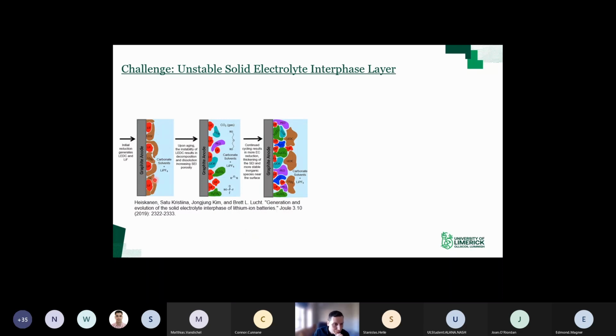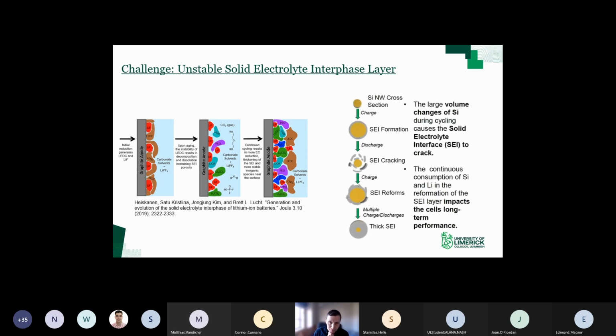Okay, so basically what happens is when you charge a lithium-ion battery at the anode, you'll get decomposition of the electrolyte. It's just unstable at those potentials. For graphite, this is not a problem because the graphite has only about a 10% volume expansion when it's fully charged. So what happens is you get decomposition of the electrolyte, and it forms this passivating surface, and that SEI layer is quite stable in a graphite anode. That's not the case for silicon.